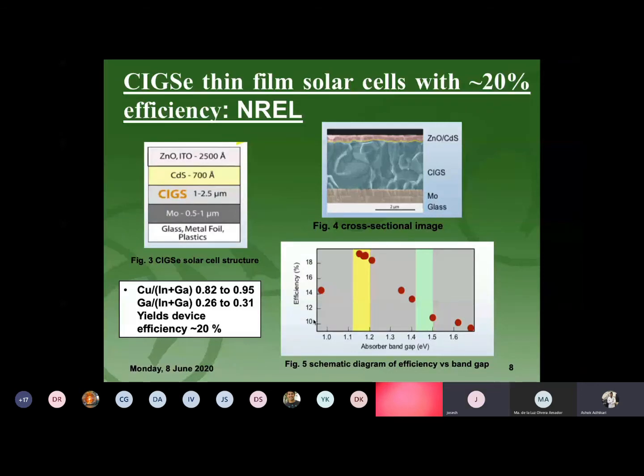As you can see from the cross-sectional image of CIGSe in figure 4, the grains are more than 2 micrometers. If you have bigger grains, the number of grain boundaries will decrease, and as a result, the number of recombination centers decreases. From figure 5, the graph between efficiency and absorber band gap, they observed high efficiency between 1.1 electron volt to 1.2 electron volt.